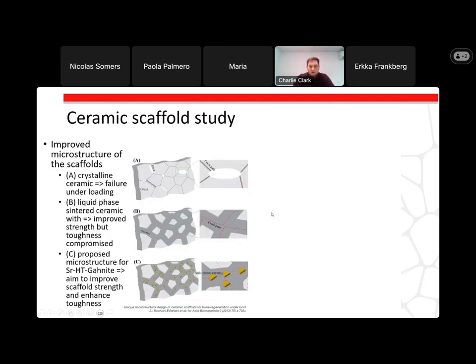So to begin with the microstructure of ceramics, there's a first type, which is the crystalline ceramic, which fails under loading. Why? Because there's normally some porosity, and with this porosity, cracks then propagate along the boundary of the grains. The second kind of structure of ceramics is the liquid phase sintered ceramic. Here there's an improved strength, but the toughness is compromised because the cracks will then propagate through this glass phase instead. So what they were trying to do with this new material was to improve the scaffold strength, but also enhance the toughness by using these sub-micron crystals that would help to deflect the path of the cracks.